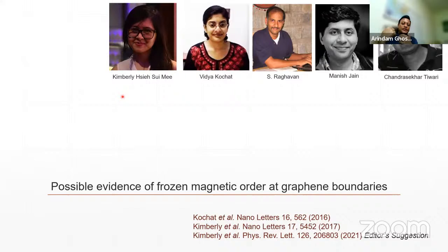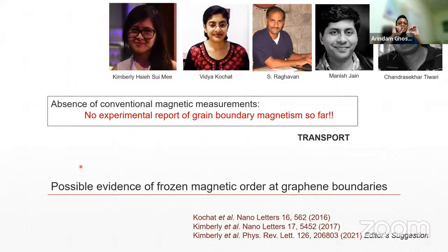In a completely different field, we asked another question, and this was Kimberly and Vidya who asked the question: if I take a grain boundary in graphene, and grain boundaries always have very large different types of defects, which are not always in our control, can the grain boundary become magnetic at some point? The difficulty in such measurements is because a grain boundary is an extremely narrow region in space, and there are very few magnetic moments, and it is very difficult to look at the grain boundary using conventional magnetic measurements. And that becomes even more difficult if your sample is cooled below, when the magnetism develops at very low temperature. So there are no very satisfactory magnetic probes. So the question is whether we can use electrical transport and noise in looking for possible frozen magnetic order in graphene grain boundaries.